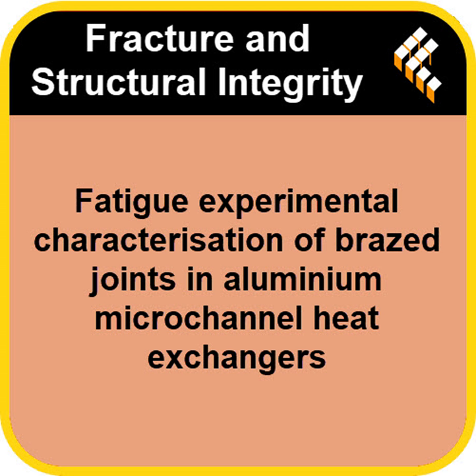Precisely. You've got it. The rolled header material suffered a really significant reduction in strength. We're talking maybe a 15 to 20% drop in its ultimate tensile strength. Wow. So the thermal cycle substantially softened it. It became less robust even before the joint was actually made. Okay, so that's the rolled header. Now, what about the extruded tube material? How did it manage to gain strength?